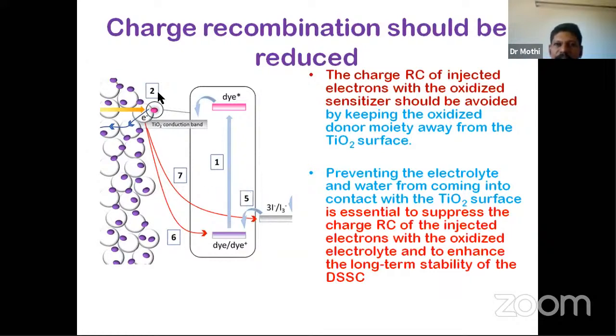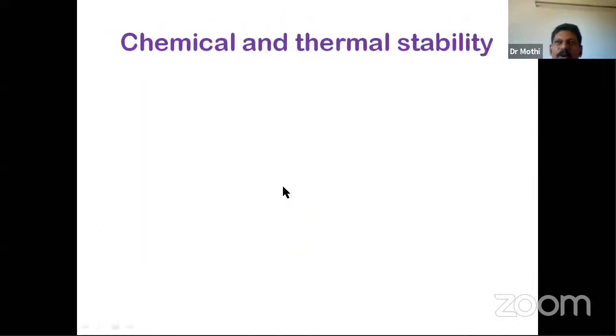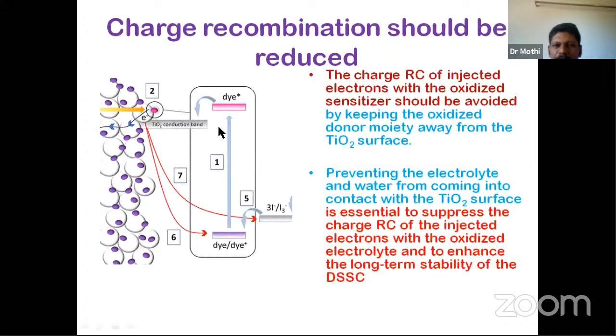So what we can do, the solution, there should be a layer or a coating in between the TiO2 and the electrolyte to avoid this recombination. Okay, so all these things can be done by designing the dye itself. For example, the dye molecule can have long alkyl chains which repel the electrolyte, which does not allow the electrolyte to come near TiO2.